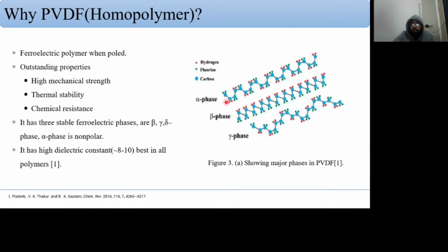Why is the alpha phase non-polar? In this figure, we can see this is the carbon chain, but the hydrogen atom and the fluorine atom attached to the carbon can be seen adjacent to each other, which cancel the charge, and thus alpha becomes non-polar. But in case of the beta phase, we can see the hydrogen atoms are opposite to the fluorine atoms attached to the carbon chain. Thus, we have a net charge here, and thus net polarization.